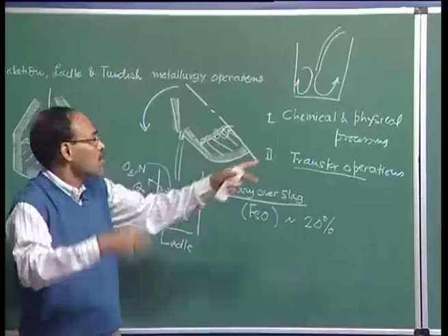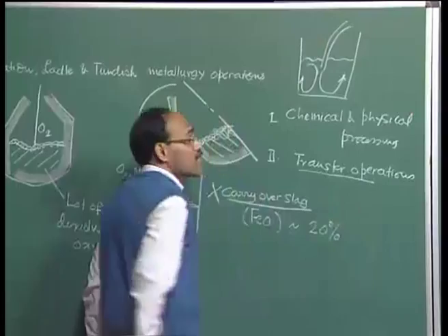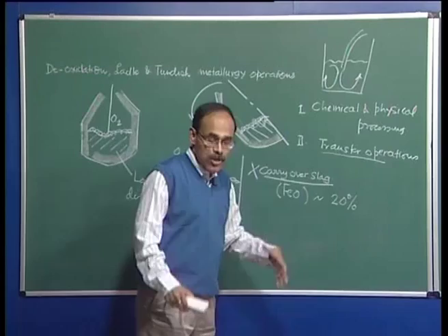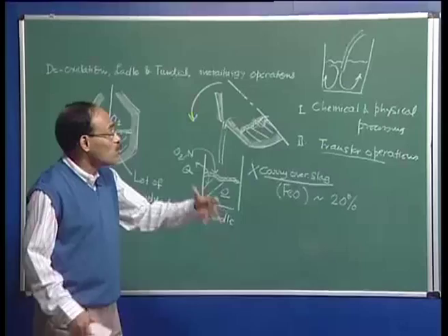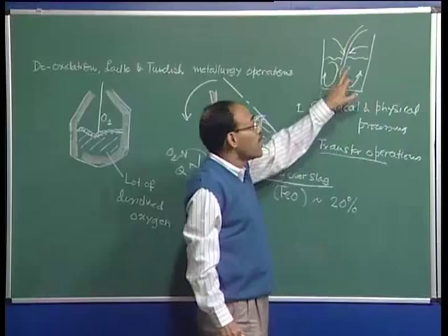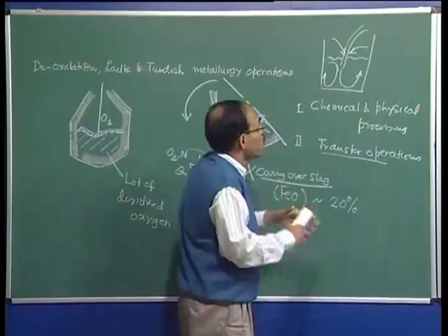And as you can witness, I would request you to go to the bathroom, take a bucket, open the tap, and observe for yourself how the bucket gets filled up. That is precisely the scenario that one would see in the case of the ladle filling operation. If you take a plastic transparent bucket, you can see air entrainment in the bathroom. So, you will see a lot of oxygen, sorry, not oxygen, but nitrogen, because the material is already saturated with oxygen. There is not much concentration gradient between the dissolved oxygen or the oxygen potential in the atmosphere and here. As a result, there will be no oxygen transfer between the molten metal and the ambient.